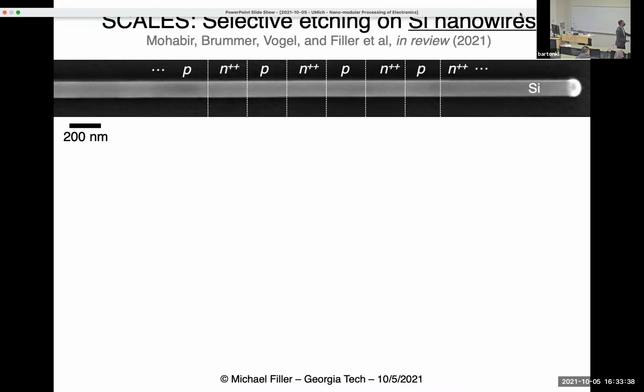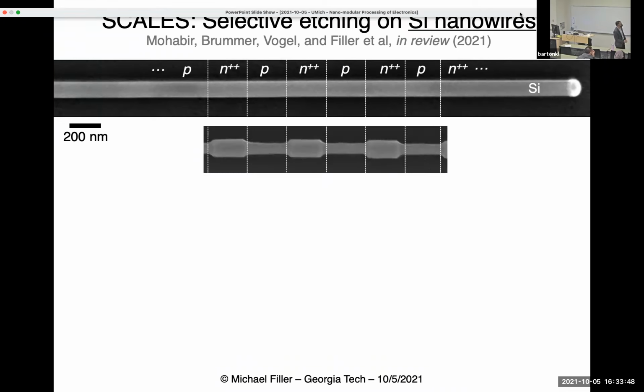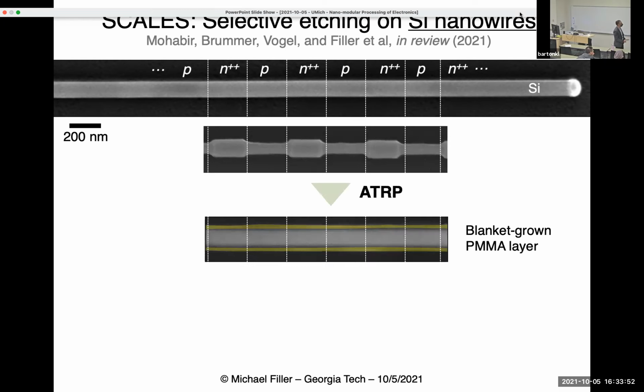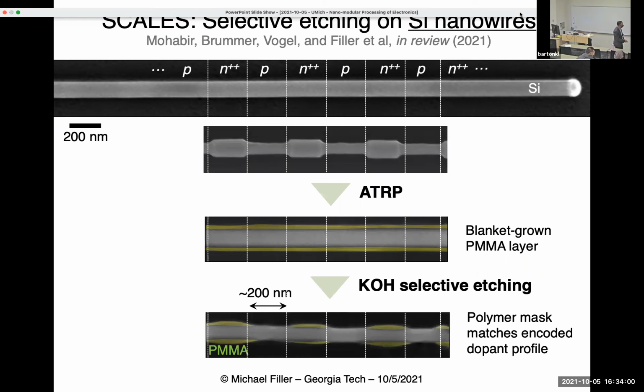Now let's do it on the nanowire. So here is another one of those test structures. You can kind of see source, channel, drain programmed along the length. Just to prove it to you, that's what it would look like if you etched it. We took a fraction of the sample and etched it, but we don't do that initially. So we start with this wire, we grow that polymer, and here I false colored it in green. And then we selectively etch it in KOH. And so if we're really careful, we can get these kinds of nanoscale masks on the surfaces of nanowires.